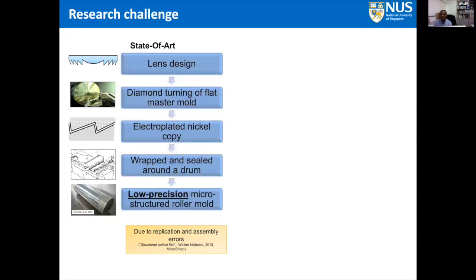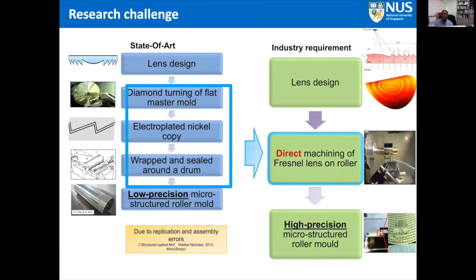However, if we do this, the accuracy and the quality is significantly dropped because it has to be fixed on the round roller. The quality of the feature that is produced is not good. Therefore, we are interested in replacing this particular technique and directly machining the Fresnel lens on the roller. If we can achieve it, the quality of the part that we produce will be significantly increased. So in this case, we do the lens design initially by means of some CAD model, and then do some simulation, and then we directly machine them by generating the tool path associated with that in order to make these Fresnel lenses, and then we do the testing on that.